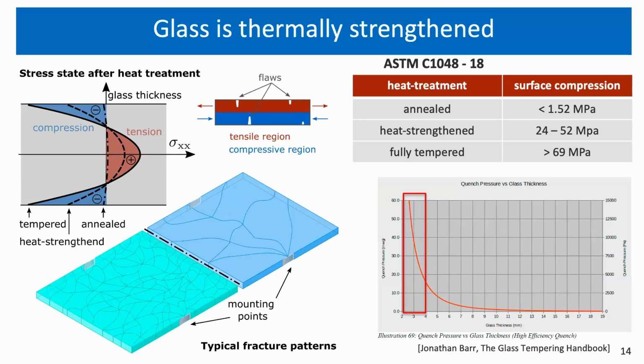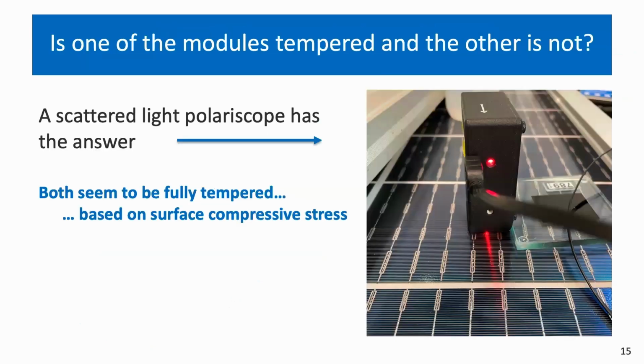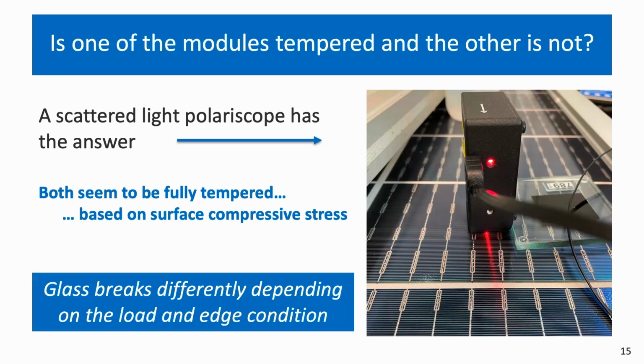And the issue with thin glass is that it's getting really hard to introduce those residual stresses, because it's difficult to cool just the outer surface of the glass while the neutral axis is still hot, to introduce a stress state. So we were wondering, maybe there are different modules, one that has tempered glass and one that has only heat strengthened glass. You can use a scattered-light polariscope to figure out the residual stress state in the glass. But once we measured them, both of those modules seem to be fully tempered, based at least on those compressive stress measurements that we did. So we weren't completely sure what's going on. How can we crack tempered glass with a single crack? This seemed a little weird to us.